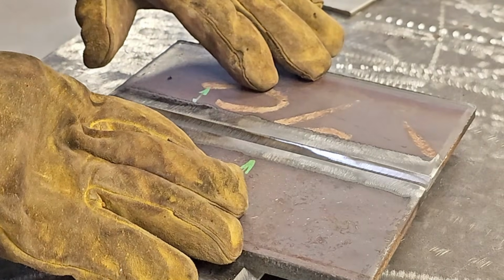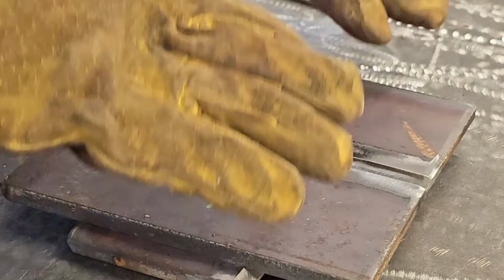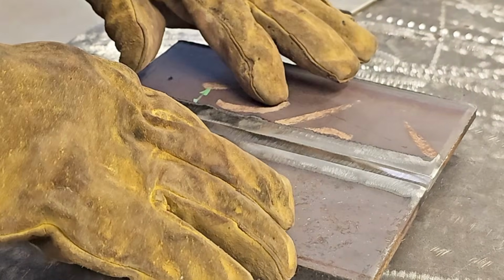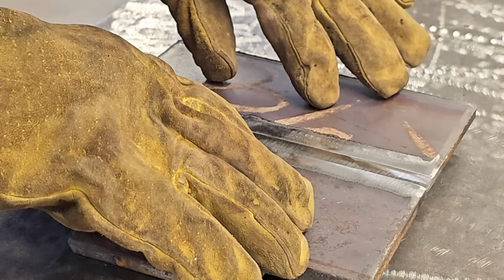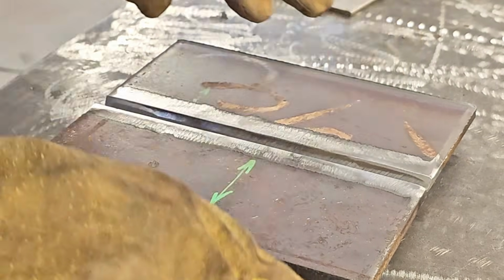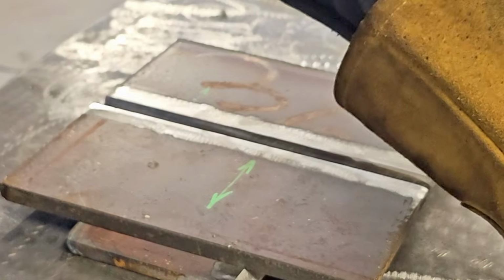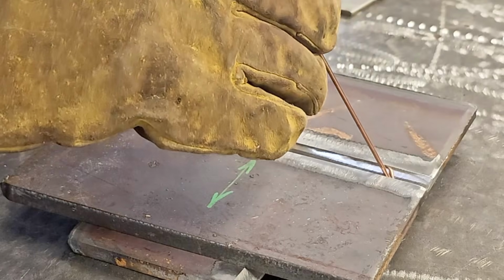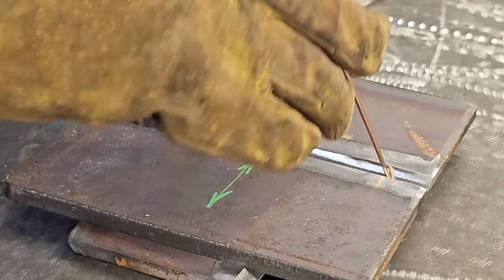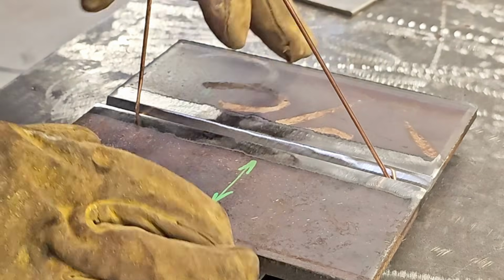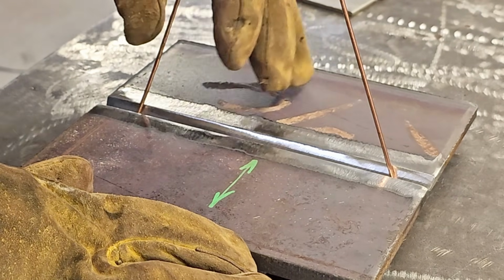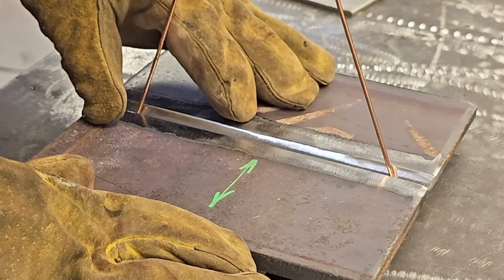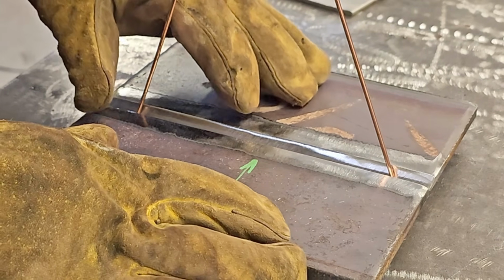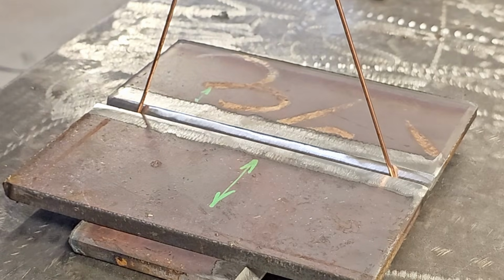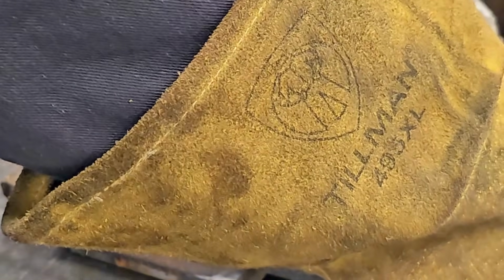Okay, so we want to set our plates on a nice flat surface because we don't want a mismatch of the root side of this. So I just have it on top of another piece of plate so that it's nice and flat. And then I'm going to use my root opening spacer here to set that root for 3/32 of an inch. I'm just going to push these together and make sure that everything is in line. And then I'm going to fit up my tabs on this side.